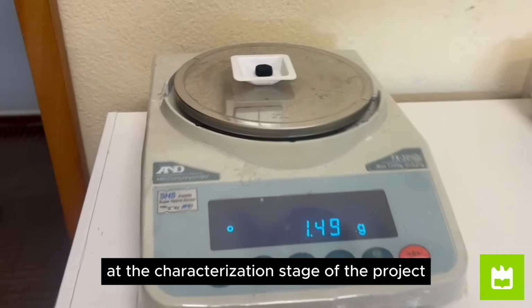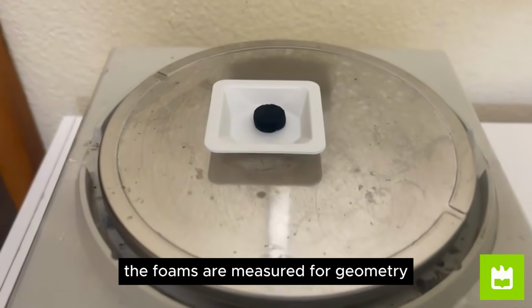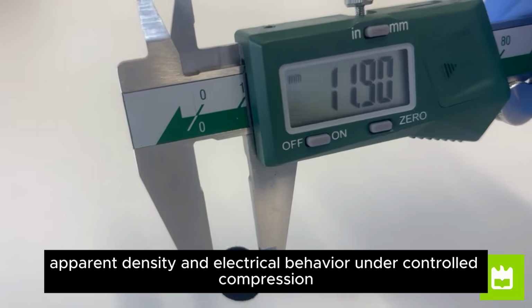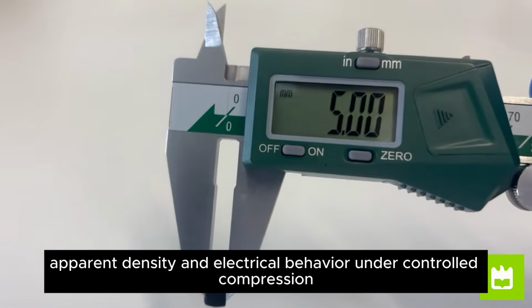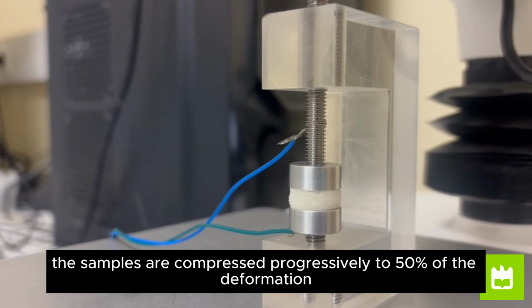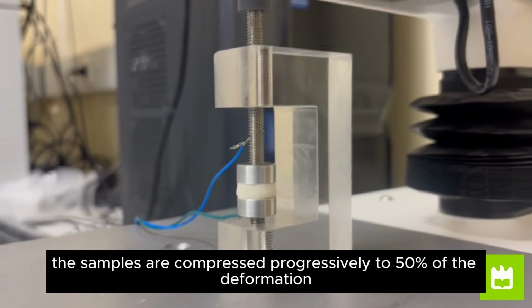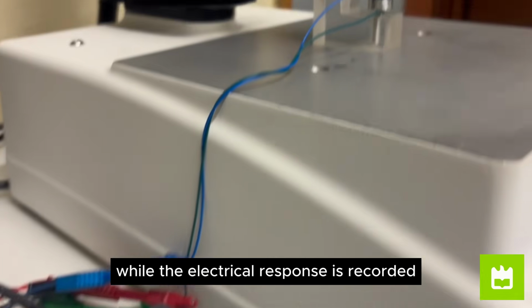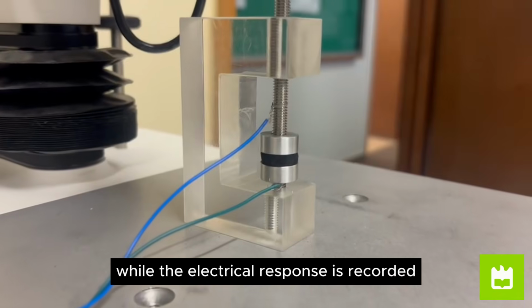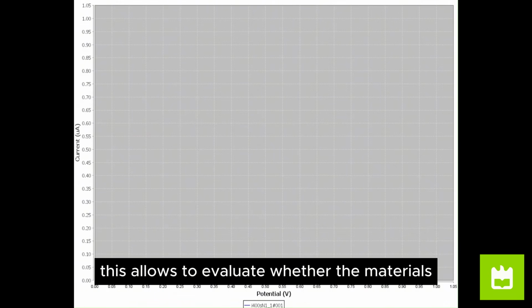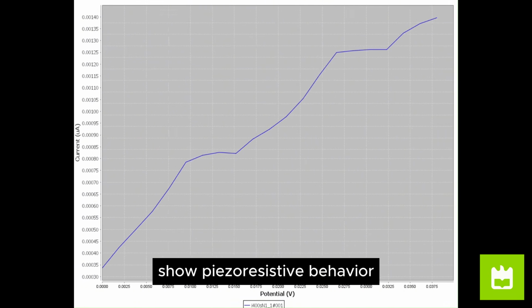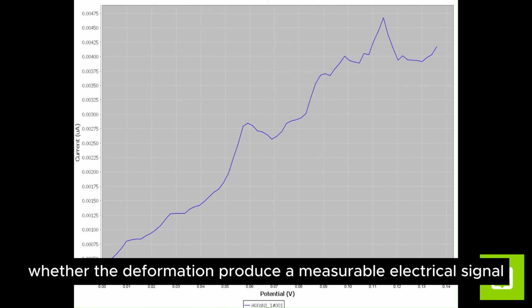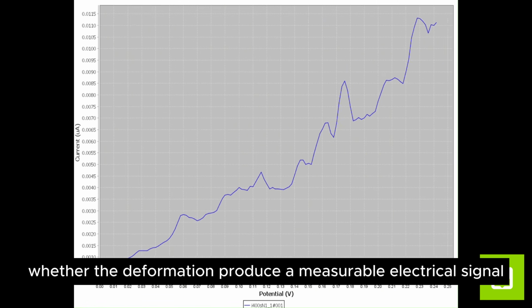At the characterization stage of the project, the foams are measured for geometry, mass, apparent density, and electrical behavior under controlled compression. During testing, the samples are compressed progressively to 50% of deformation, while electrical response is recorded. This allows us to evaluate whether the materials show piezoresistive behavior. In other words, whether the deformation produces a measurable electrical signal.